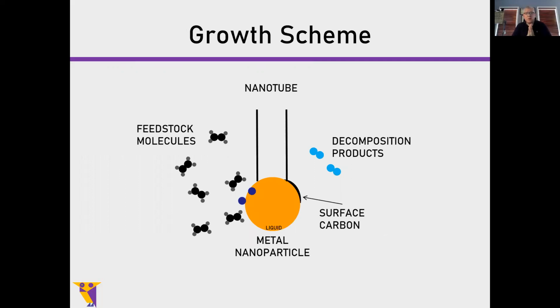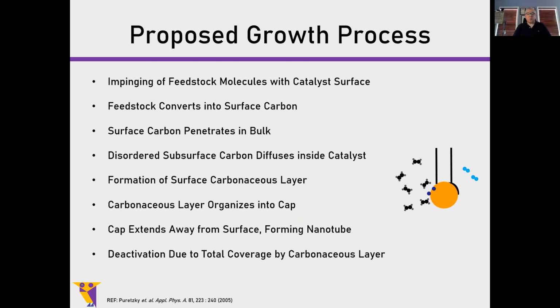If you take a look at a standard proposed growth scheme for nanotubes, you start off with a metal nanoparticle in a liquid state exposed to a feedstock molecule. What happens is that that feedstock molecule will land on the surface. It will form a surface layer. Decomposition products will move off, and then the carbon will rearrange itself and form a nanotube. So that's the proposed growth process. And you can see that this has been proposed a long time ago. It's 15 years old. And these are the steps that were proposed for how this worked. And it was also observed in TEMs.